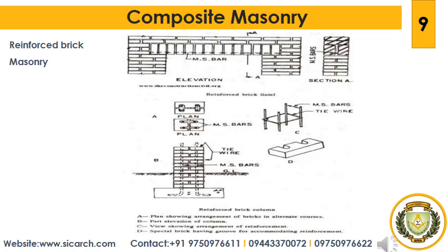The sixth and last type is reinforced brick masonry. Brickwork strengthened by the introduction of mild steel flats, hoops, iron, expanded meshes, or bars is termed as reinforced brick masonry. It is capable of resisting both compressive as well as tensile and shear stress. On account of its ability to resist lateral forces, reinforced brick masonry is extensively used in seismic areas. It is essential to use first class bricks having a crushing strength of 140 kg per square cm or more, along with rich and dense cement mortar.